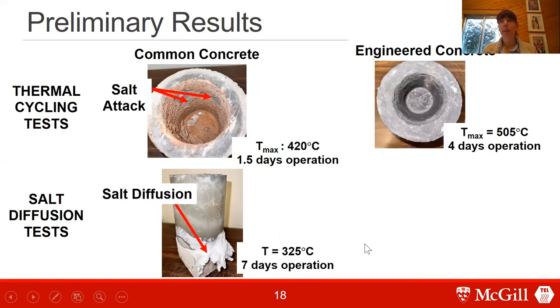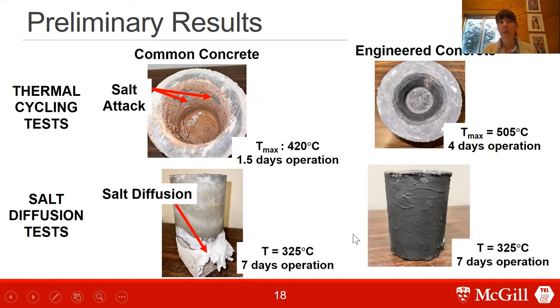So looking now at our engineered concrete, you can see for our thermal cycling tests, we have no issues in terms of salt attacking the concrete itself. And similarly, no issues in terms of salt diffusion. So we don't have this issue of salt literally pouring out of the sides of the walls. And this was carried out for 7 days of operation. So we're continuing to develop these experiments in the lab, ideally with the hope of commercializing a higher temperature chloride-based CSP pond system.